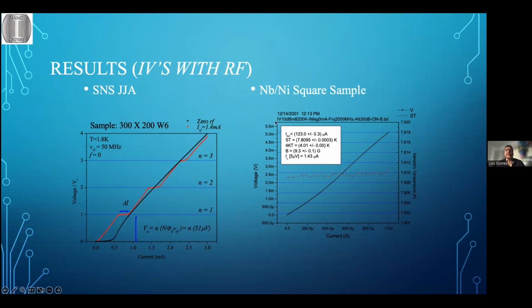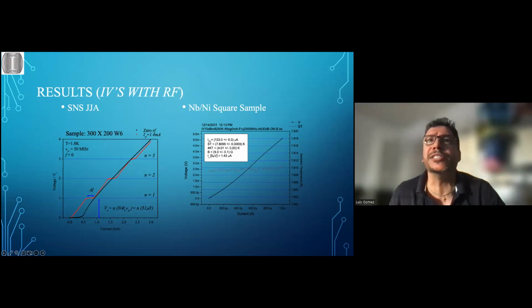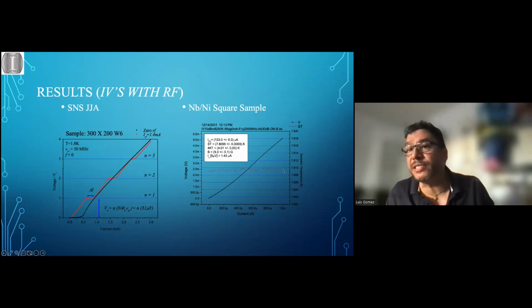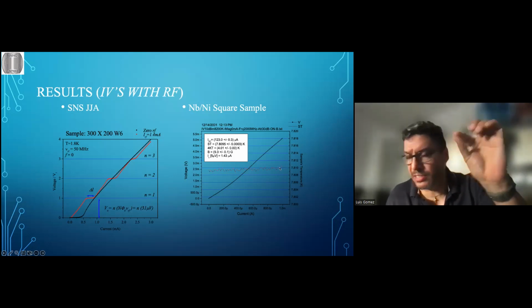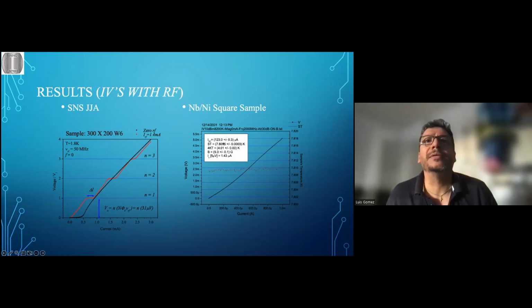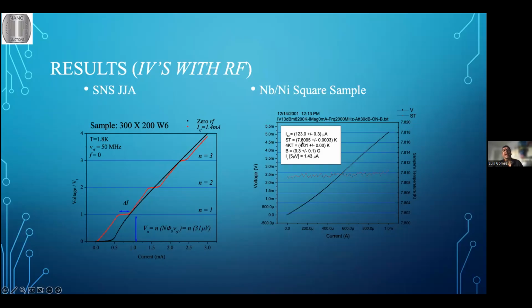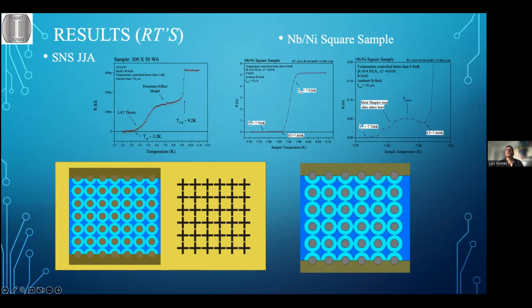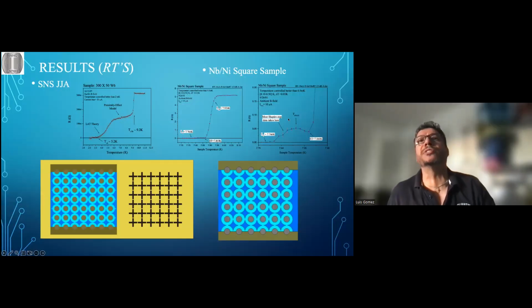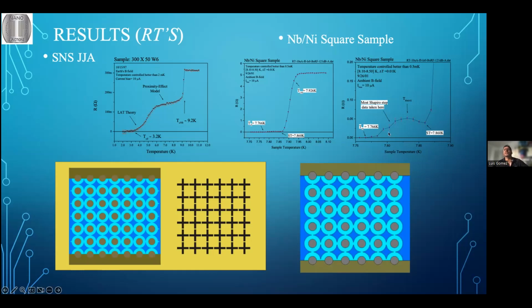Now I did the same thing for the niobium nickel sample, and I just didn't see that change. Again, the ST here represents how the temperature changed in the system. There are many measurements of each point, so the error is very small. Then I tried to do the experiment at a particular value, 7.8 kelvins. If I show you the previous slide, 7.8 kelvin is right here. This is where most of the Shapiro steps data were taken, around this region.